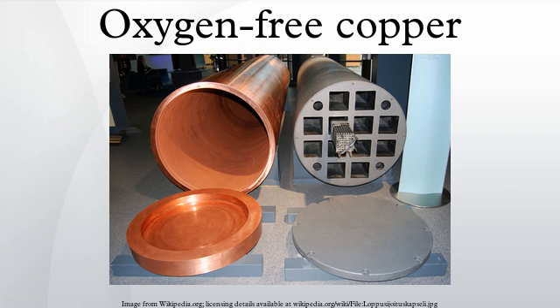C10100, also known as oxygen-free electronic (OFE), is a 99.99% pure copper with 0.0005% oxygen content. It achieves a minimum 101% IACS conductivity rating. This copper is finished to a final form in a carefully regulated, oxygen-free environment. Silver is considered an impurity in the OFE chemical specification, and it is the most expensive of the three grades.